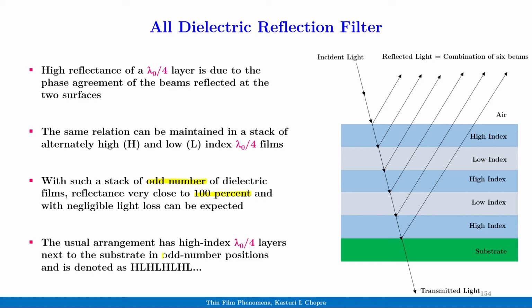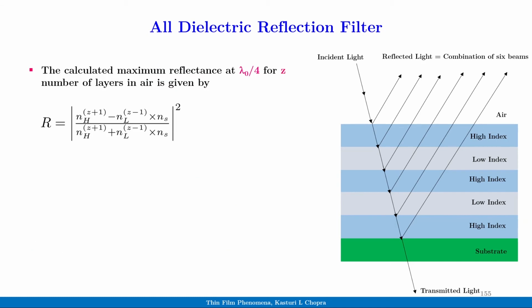The usual arrangement has high index lambda 0 by 4 layers next to the substrate in odd number positions and is denoted as HL, HL, HL, etc. The calculated maximum reflectance at lambda 0 by 4 for Z number of layers in air is given by R equal to modulus of (NH to the power Z plus 1 minus NL to the power Z minus 1 times NS) over (NH to the power Z plus 1 plus NL to the power Z minus 1 times NS), the whole squared. Here, NH, NL and NS are the high, low and substrate indices.